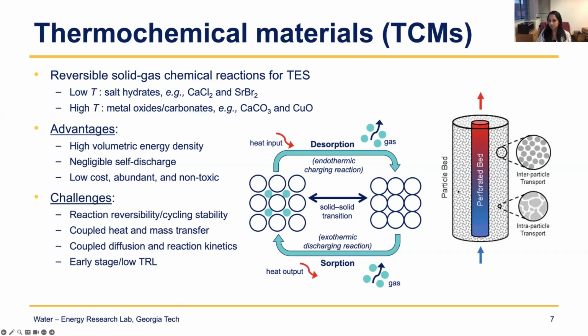What we study are these materials put into reactive beds. This is an example of a packed bed reactor where you have some inner pipe for fluid to flow to either charge or discharge. And then you have your particles, which are the salts or the limestone, packed at some packing density. Between the particles you have transport occurring, so that's interparticle transport. And then within each particle, they're also porous, so you have intra-particle transport as well. So you essentially have heat and mass transport within this type of reactor at these different length scales. There's diffusion, and then there's chemical reaction as well. All of these coupled effects are what we model using heat and mass transport models, as well as chemical kinetics or rate models.